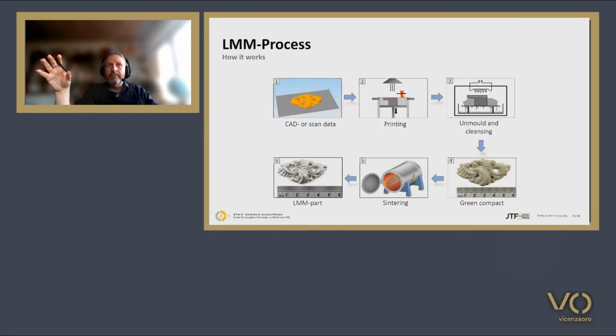How is it working? It's not, as with laser powder bed fusion, a direct process where you get your part directly when you print it, but it's a so-called indirect or sinter-based process where you first print the green part and then remove the plastics. So you start with the CAD or scan data. You do the printing, and then we have a special procedure which I will show you in a bit, which is the unmolding and the cleaning of the part. Then you get a green compact, which goes into the sintering furnace, goes through a certain shrinkage, and then you have your LMM part, or lithography-based metal manufacturing part, because that's such a monstrous word, we call it LMM.